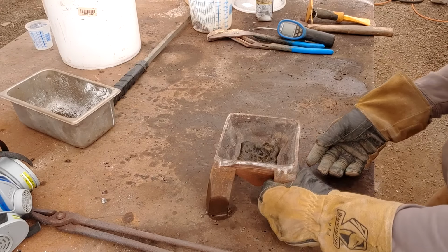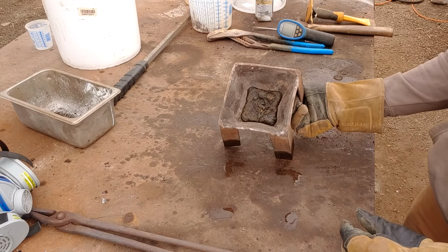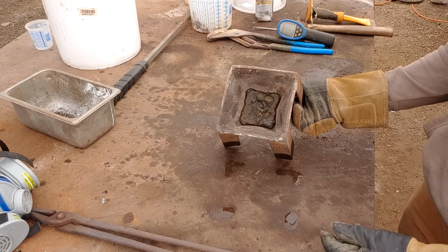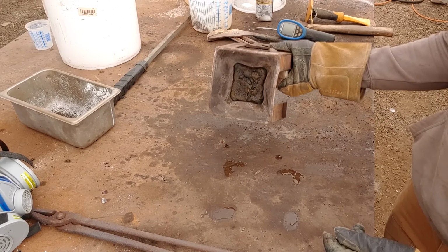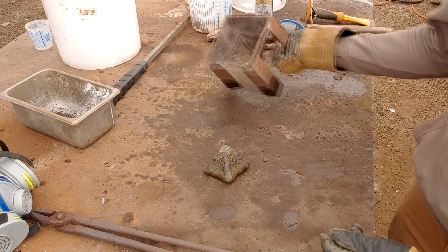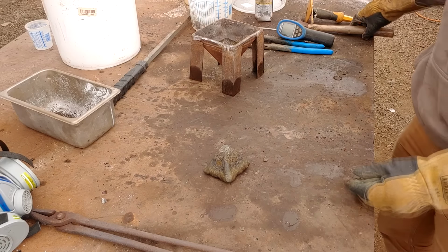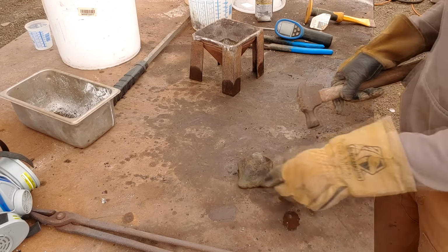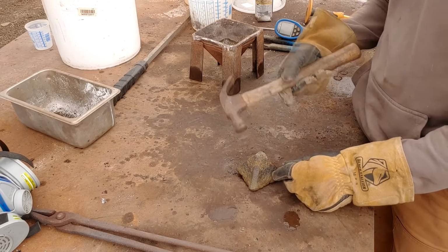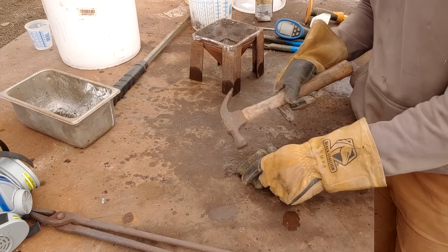Well, this is all our slag, and I added a bunch of iron to it to try and reduce out all the lead and copper we oxidized. Let's see what we got. Now, unfortunately, it was my last smelt with that crucible, and the crucible leaked. So I leaked all my slag all over the furnace.